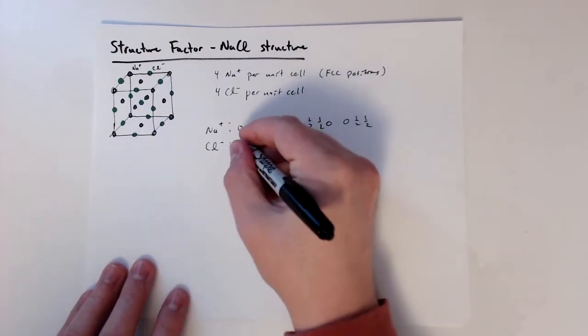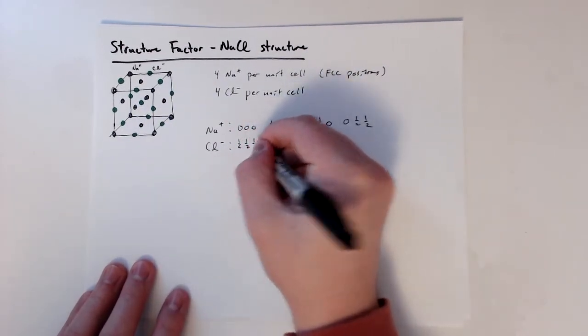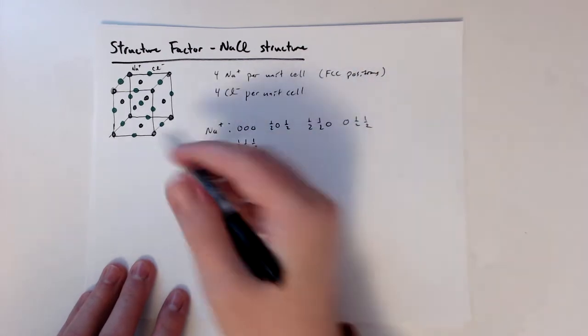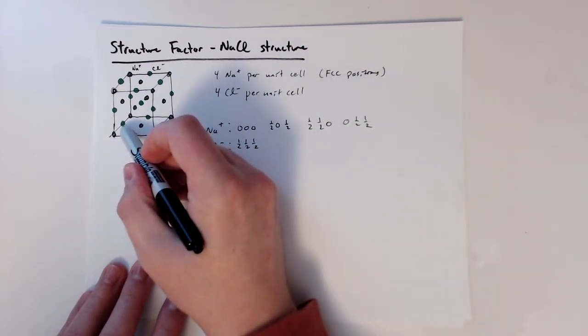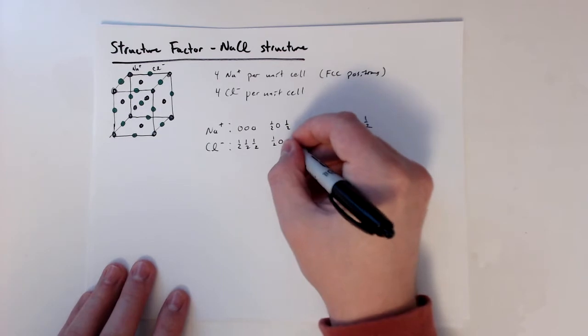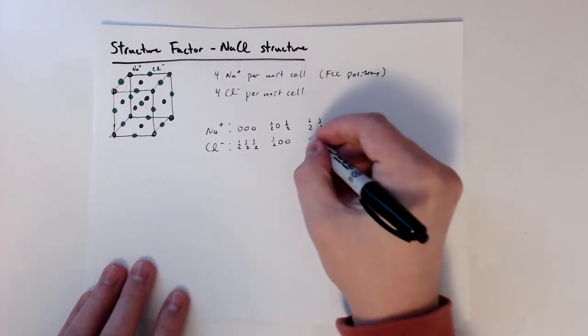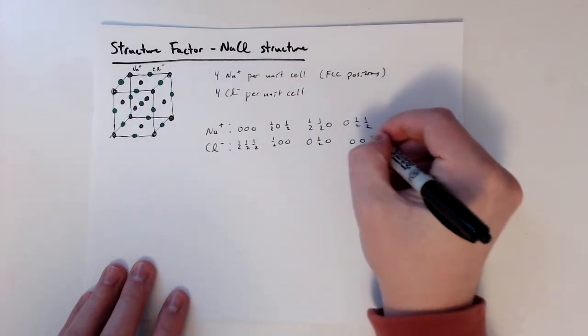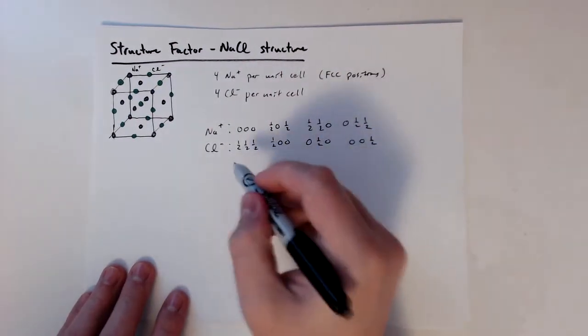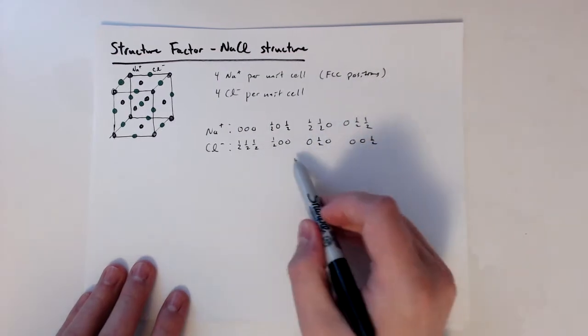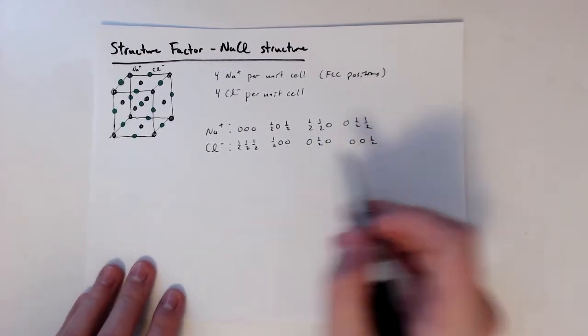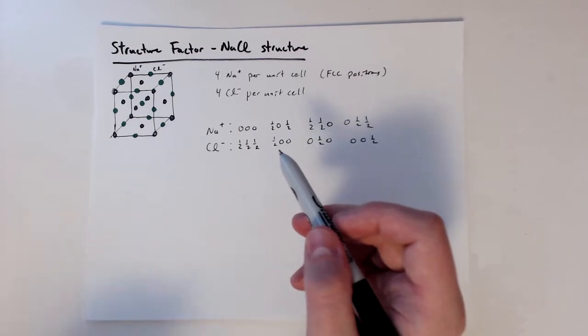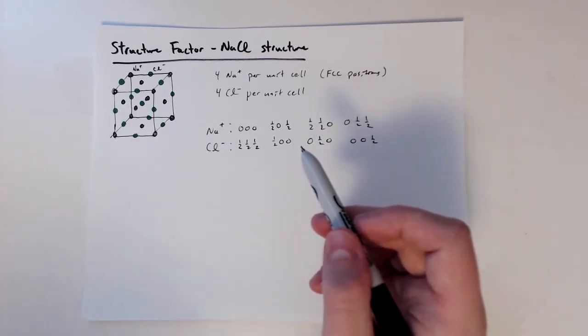So we know that the center of the unit cell is the body centered, and that's 1/2, 1/2, 1/2. And also if they're on the centers of these edges, that is of the type 1/2, 0, 0. So I've got 1/2, 0, 0. There's also one over here, so 0, 1/2, 0, and then also 0, 0, 1/2. So that would describe all the positions. Again, even though there are more of these edges, they're sharing, so we only need to identify 3 of them.